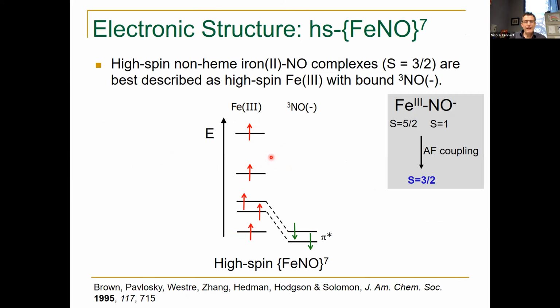Yeah. So as I mentioned, these have been studied for a while, starting with this very important paper by Ed Solomon's group from 1995, where they looked at this first using especially X-ray absorption spectroscopy and also vibrational spectroscopy and MCD. And what they found is that these complexes are actually best described as high-spin iron-III NO minus, where the NO minus is in the triplet state, as you can see indicated here in my little bonding diagram. So we have a high-spin iron-III, all spins parallel, and then here is our triplet NO minus. So it has a very different electronic structure than the heme system, although they're both FeNO7s.